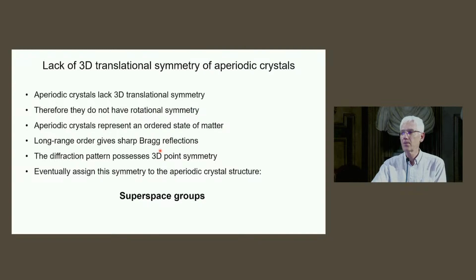Nevertheless, we now know that an aperiodic crystal is an ordered state of matter, most effectively pronounced by diffraction, where we see sharp Bragg reflections for the aperiodic crystal as well as for the crystal with translational symmetry, but they cannot be indexed with 3 integer indices. So long-range order is reflected by sharp Bragg reflections, and the other way around also, sharp Bragg reflections you have when there is long-range order.